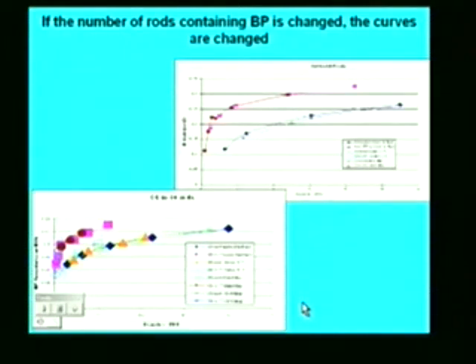If we change the number of rods that we put the burnable poison into, now the curves are different. They don't lie in the same place. And if you track some of the numbers here, in this set of curves for 16 rods versus 64, you find it doesn't hold. The curves are very different.